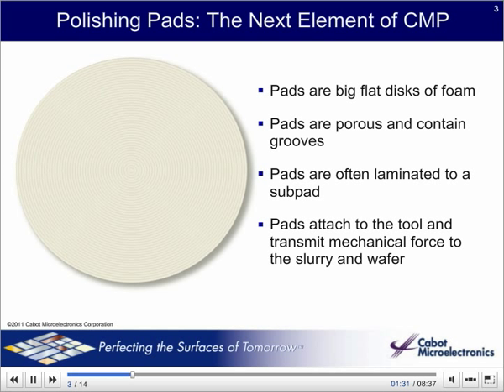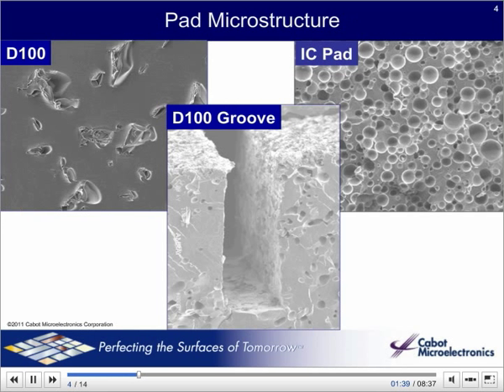Why don't they last forever? To understand this better, we need to look in more detail at their structure and how they are made and used. Pads generally come with grooves and pores, as you can see in these micrographs. Our understanding of pad mechanics is not complete, but we do know that grooves are important, mostly for transporting slurry into the process and polishing byproducts away from the process. Pores also play a critical role in holding slurry close to the wafer.